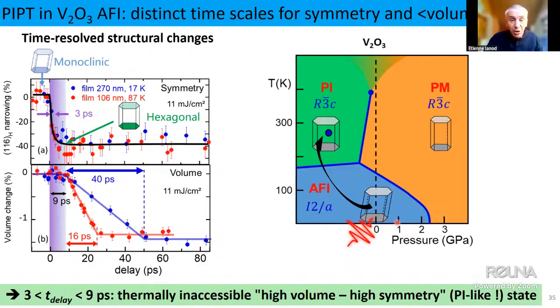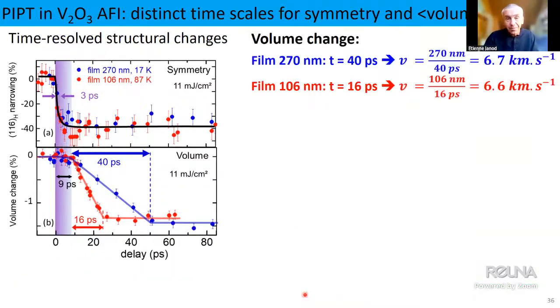But its symmetry has increased, and in fact we have a phase that looks exactly like the PI phase which exists in the phase diagram, and this behavior is completely impossible when we do only thermal. Thermally, this is not what happens. We never see the appearance of it when we warm up this system. So it's a state that is accessible only through this excitation.